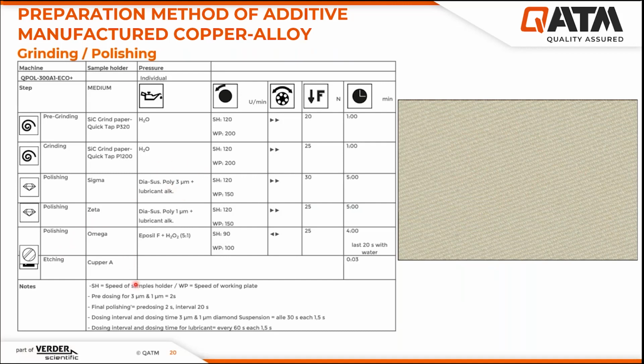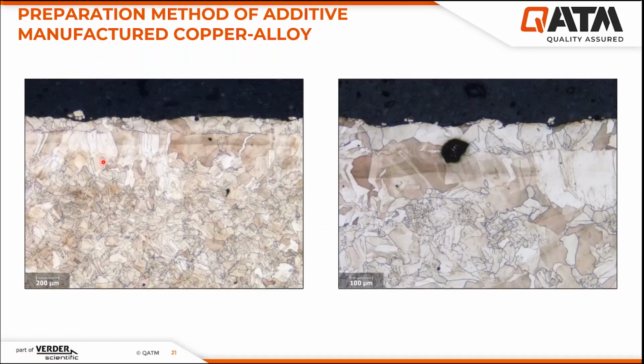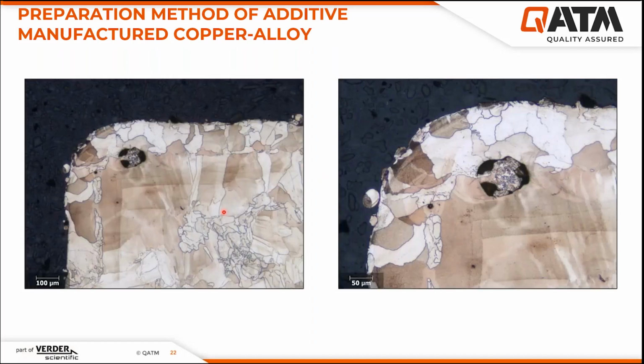The etchant here is copper A. After etching, you can see the edge of the material, the outline without any rounding. Then you can see the coarse grains on the edge of the sample, and on the core area you can see the fine grains. To see the grain boundaries between these grains, it is very important to not have deformation in your preparation. The metallographic preparation is very important here to have very clear grain boundaries.